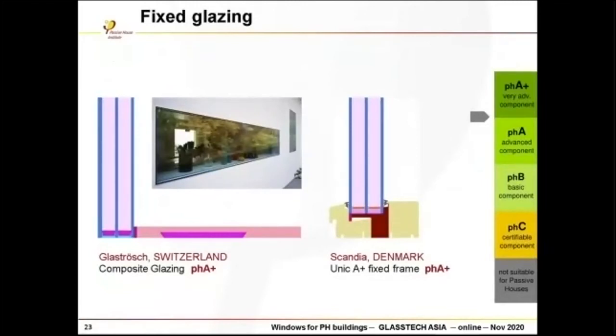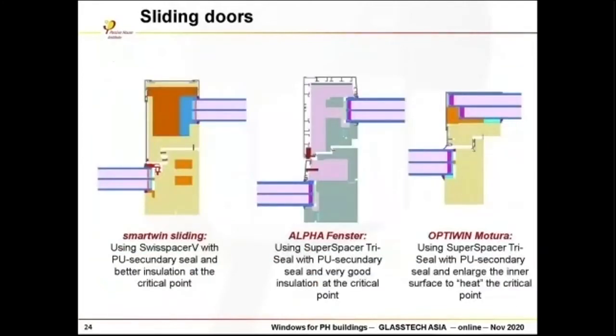Well, the next point is fixed glazing. Again, here, if you do a detailed design and check for all the heat losses and the geometry, you can get, as is shown here, a very nice view with a very slim frame and very low thermal losses. Here a little bit different, but you see, it's possible to go for fixed glazing with slim frames. Well, for sliding doors, the challenge is to have it airtight and thermally insulated. And you see here as well, three possibilities.